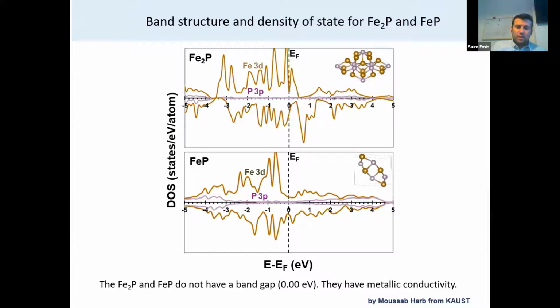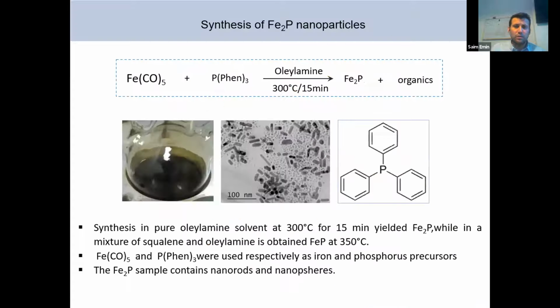The metal phosphide we used was iron phosphide. Iron phosphide can appear in several phases: Fe3P, Fe2P, FeP, and FeP2. When we increase the content of phosphorus, they become semiconductors. These two are metallic. We also calculated the density of states. The calculation was done by Dr. Moussab Harb from KAUST. The density of states is known for this material, but we use it for some other purpose, which I will not show here because it's about a different study. However, I can say that these materials are metallic.